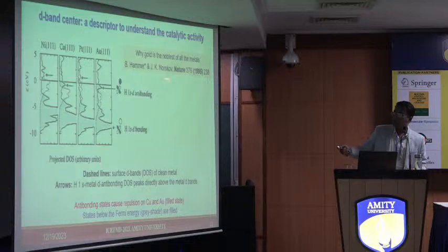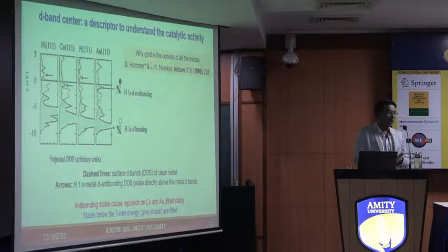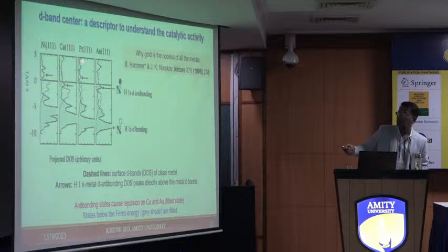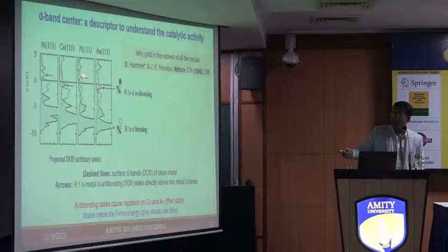Now, if you look at the paper by Norskov in Nature, what they tried to present is why gold is the noblest of all the metals. They theoretically compared nickel, copper, palladium, and gold. And what they found is that the density of states near the Fermi level is an important parameter. And this is the d band. So if you look at the d band structure, and particularly the d band center, the d band center plays an important role.